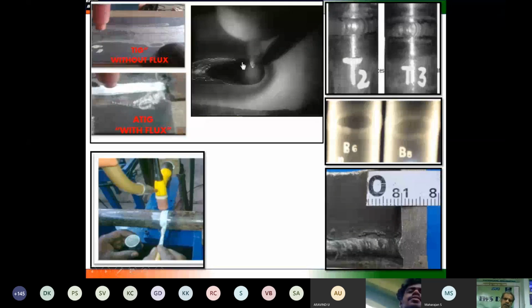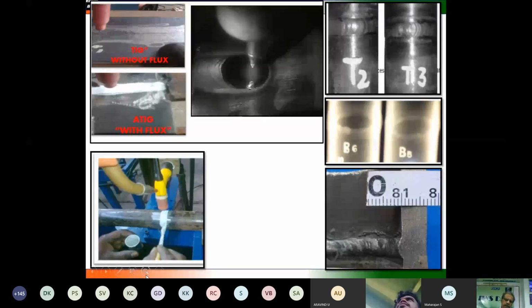Here the procedure is to take the flux, mix it with acetone, apply it over the surface, and then do the welding. Only one thing we tried. Actually, I cannot say it is not possible.